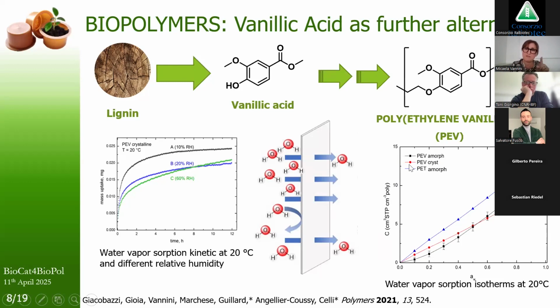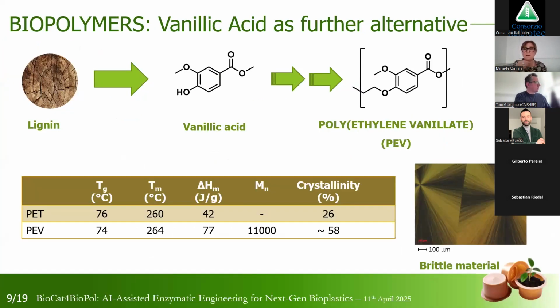both PEV amorphous and PEV crystalline absorb only a minimal amount of water, and this amount is in any case lower than that absorbed by PET, suggesting better barrier properties of PEV than properties of PET. So PEV can be considered a bio-based alternative to PET.